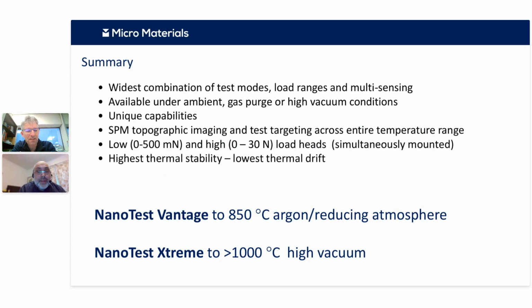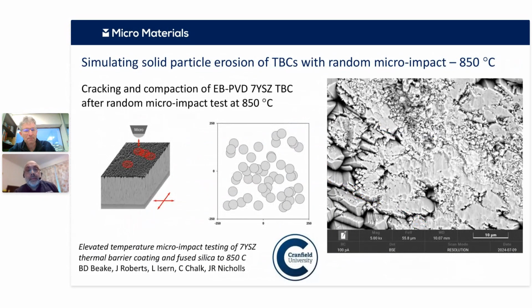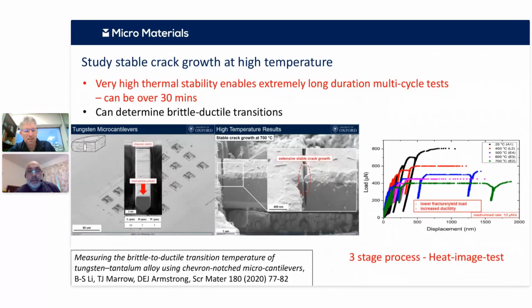Well, I think James answered it quite well. Bo's test technique really did have this notch geometry that was a critically useful thing in terms of getting the crack started. You can see right there in the middle, he's created this chevron geometry, and there's a very slow extension of that small crack in the middle that's being studied in the test. So obviously there are different types of geometries that you can use, but I think the work that Bo and James have done at Oxford and UKAEA is giving us lots of confidence that you have this flexibility.